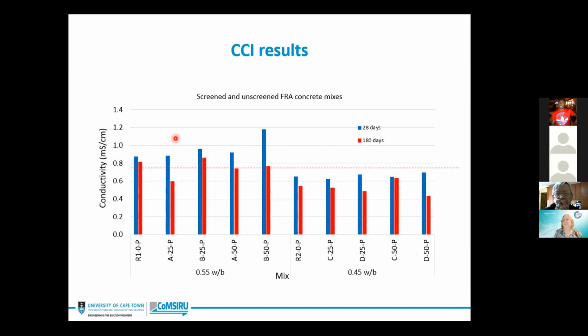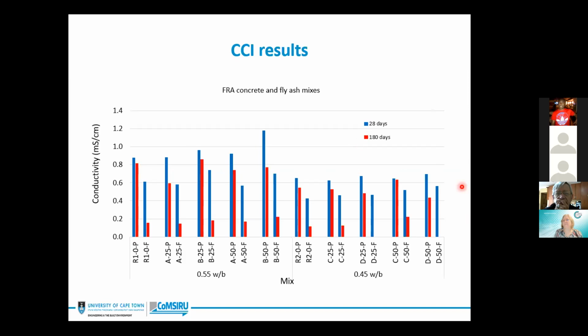For CCI results, we can see that the concrete quality, of course, lies between good to excellent, particularly for the 0.45 mixes. Of course, this is due to their low water content and therefore denser microstructure. On addition of fly ash, results improved significantly, especially over a prolonged curing period.